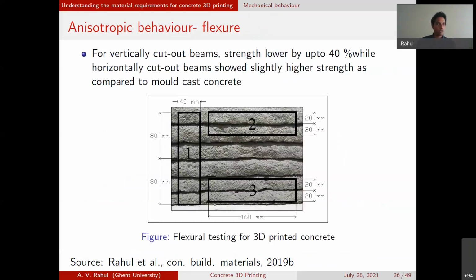This anisotropic behavior you also see in flexural loading. For example, if you have beams cut out, say from directions 2 and 3, and you also have a vertical beam, you would see different flexural strength obtained for both these cases. This again is very clear if you look at where the peak stresses are occurring. Let's say if you have this beam 3 here, and you're doing a single point bending test, you will have the maximum bending moment at this point here, and the maximum bending stress occurring at the extreme fiber here.